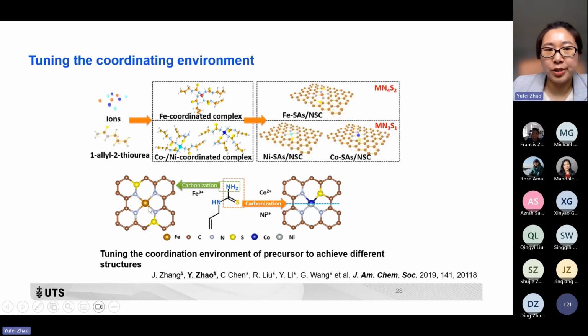For the iron, we can see it formed an atomic structure with the iron directly bonded with 4 nitrogen, and the sulfur atoms are in the second coordination shell. For the cobalt and the nickel, it's different. We can see they bond with 3 nitrogen and 1 sulfur here. So the different atomic structures between the iron, cobalt, and nickel may lead to different charge or electron transfer in these atomic structures. And that will make the center metals have different charge density, so they show different performance for this ORR.